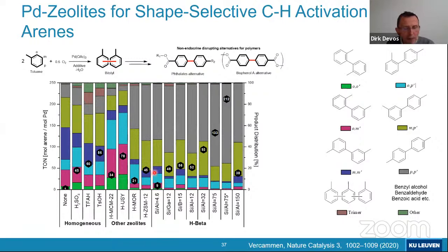But then we were very surprised and also pleased to see that in zeolite beta, you start to have very strong deviations from the statistical product distribution. And for instance, you make a lot of the para-para isomer. And that's, of course, quite a surprise. You wouldn't think how this is possible because these concepts of palladium molecular catalysis had before never been implemented in a zeolite, but somehow the palladium beta catalyst makes a lot of this para-para isomer.